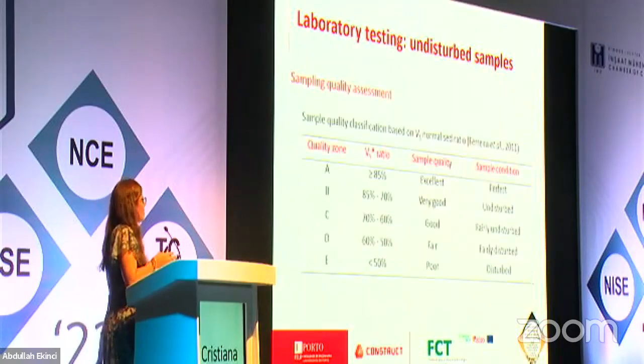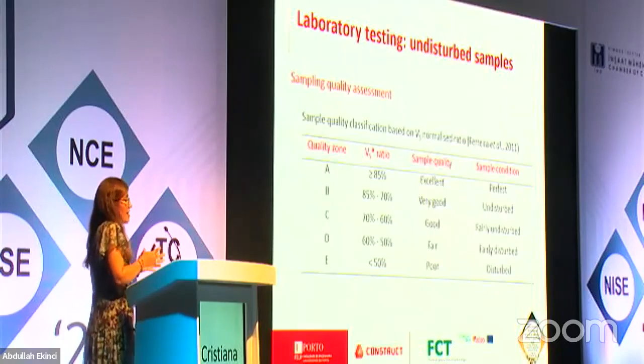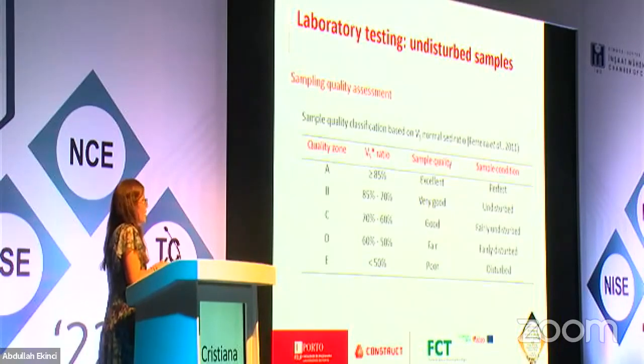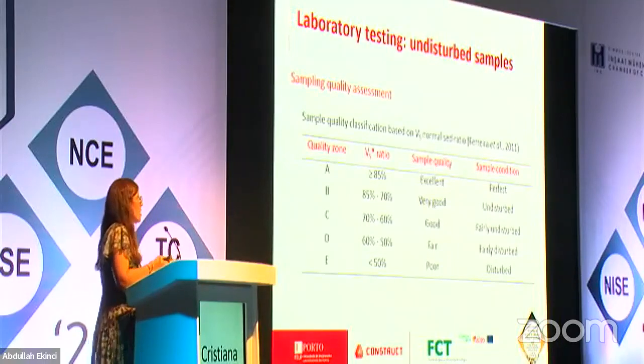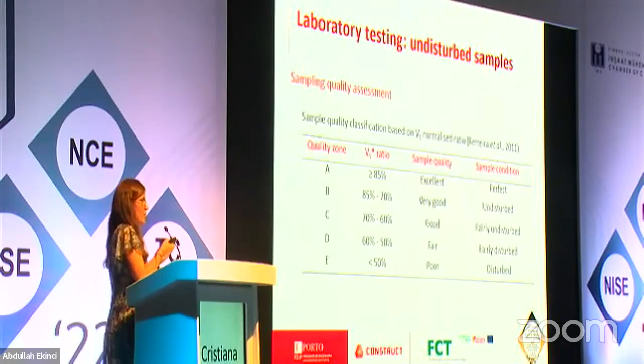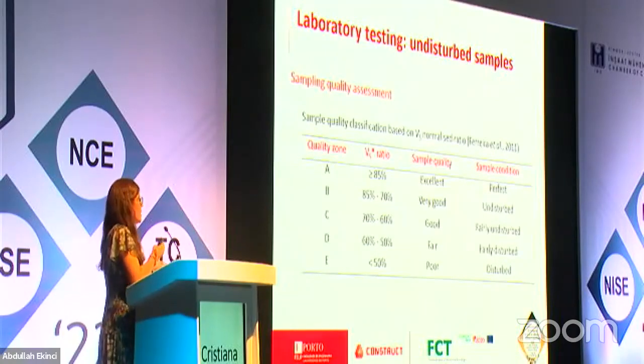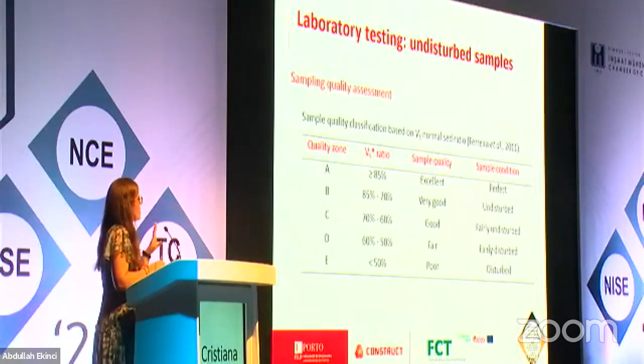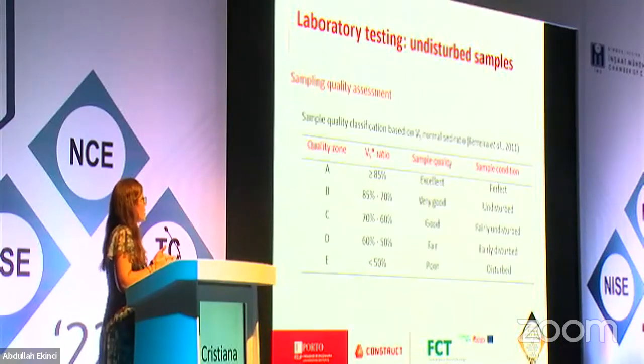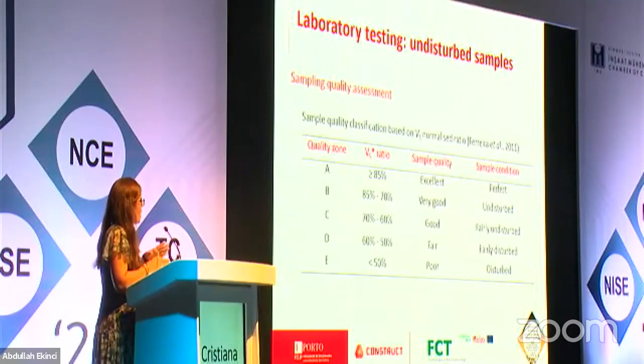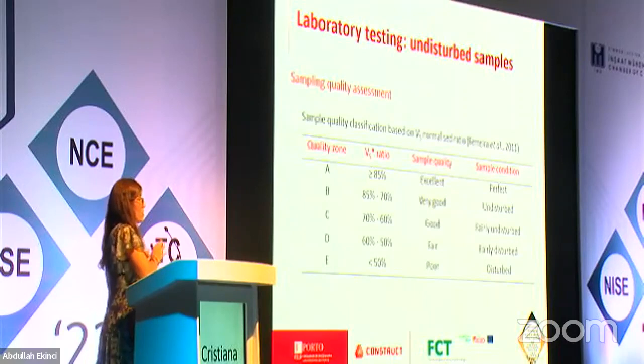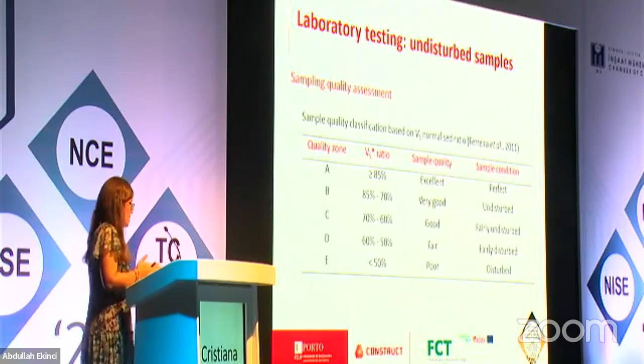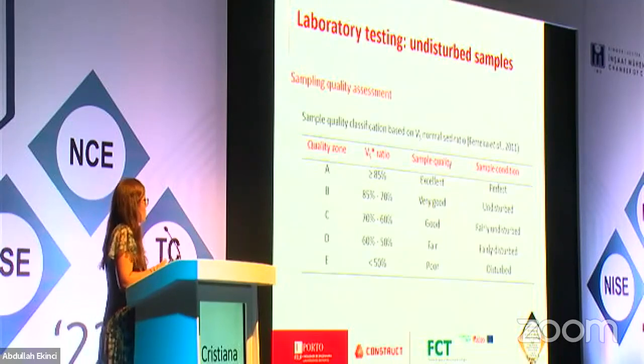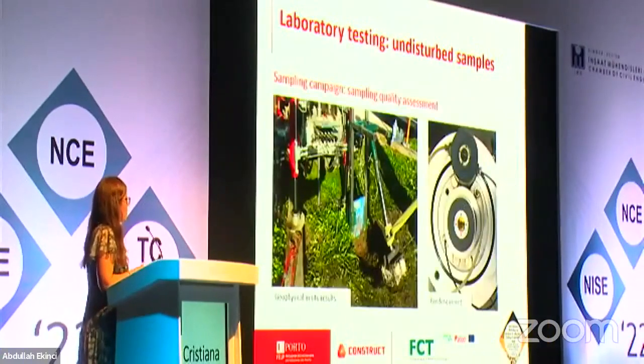And so after we did this, we wanted to check and assess the sampling quality that we were obtaining by comparing the shear wave velocities in the field to those that we obtained in the lab. And we did this in 2 stages: at bench test, that is immediately after extrusion, and also in the cyclic triaxial test like you saw here. And as a reference, we use this sample quality classification that was developed during my PhD in Porto. This was developed for sands or silty sands, so it's different from the classic clay sample quality evaluation. And we're going to compare the normalized shear wave velocities, as I'll show later on.